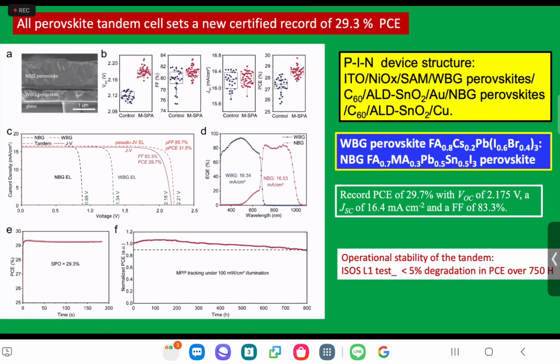So almost all the parameters go up, including the power conversion efficiency, and stability-wise, you still have some work to do, but that's true for all tandems. It's not so bad. You get 10% over beginnings, I think, but there is some kind of a hump here. So that's a bottom cell, I think. There's an issue with the bottom cell because we had excellent stability for the top cell. And the bottom cell has tin in it, and so still you have to work on those mixed tin formulations.